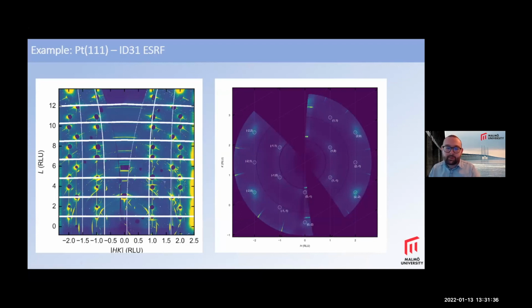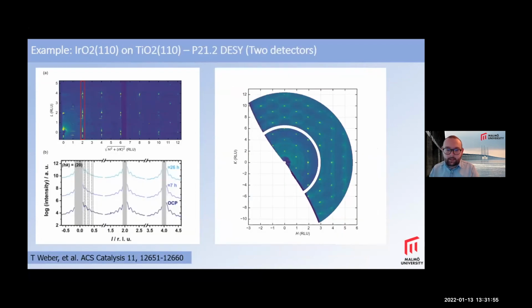Some examples. So this is an example where we've used it from the ESRF on a platinum 111 sample. And you can see one of the advantages of this high energy surface X-ray diffraction is you can really collect a lot of CTRs. You can get the symmetry equivalents and really normalize your data quite nicely.